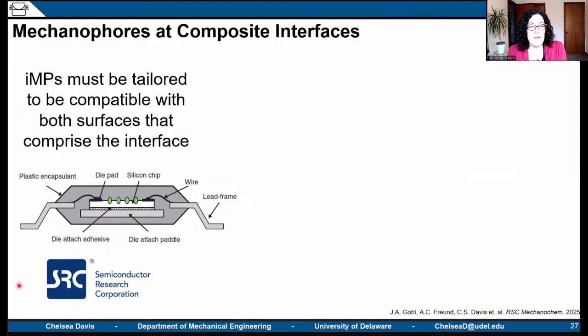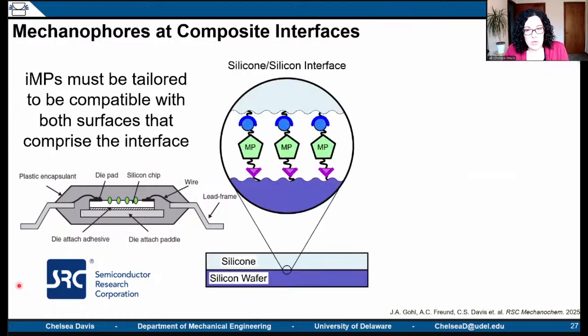And if the interface fails, you have to be able to detect that delamination or debonding event before it's big enough that you can see. And we thought mechanophores might be a really exciting way to interrogate molecular scale or even sub-nanometer separations in the interface. So in order to do this, you have to think about designing a mechanophore, and this is the challenge for the chemists on the call.